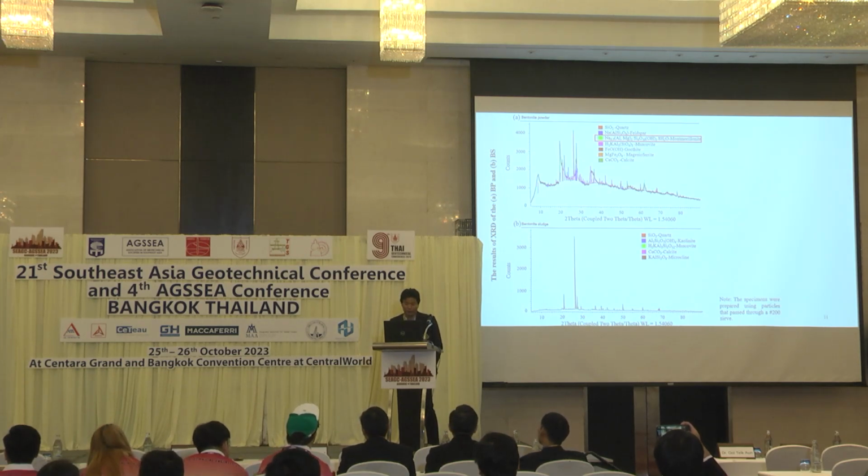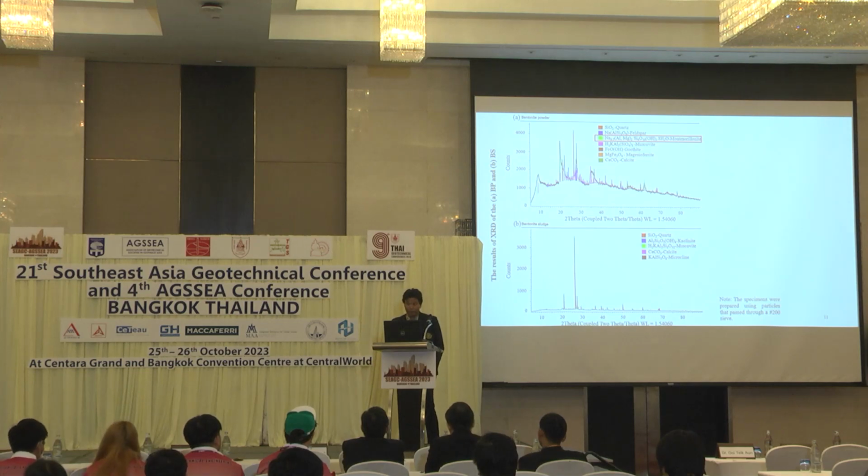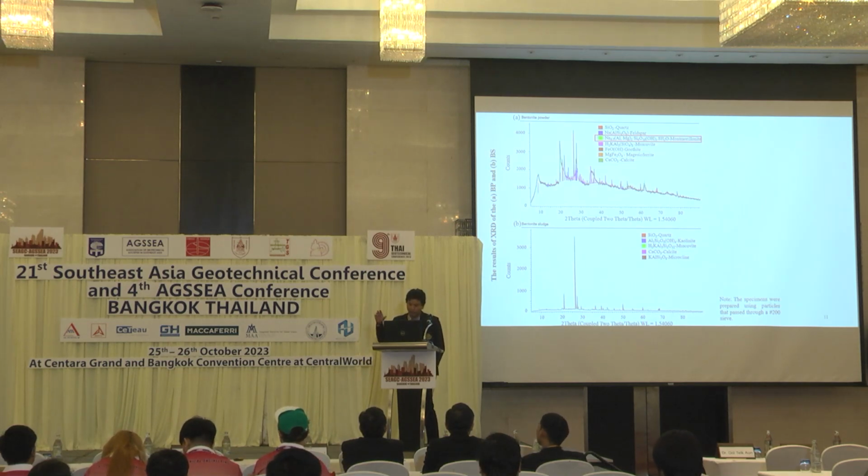But after we treat it using the anionic polyacrylamide, in the below figure, you cannot see the montmorillonite. The montmorillonite, I think you know, has the 2-to-1 structure, and between the interlayers there is a positive ion, and when water comes, it absorbs much water. So that is the reason why the liquid limit of the BP is very high.